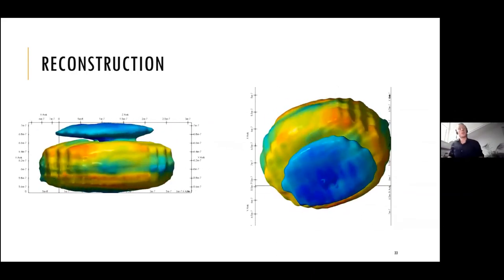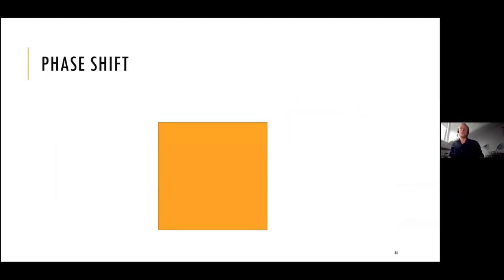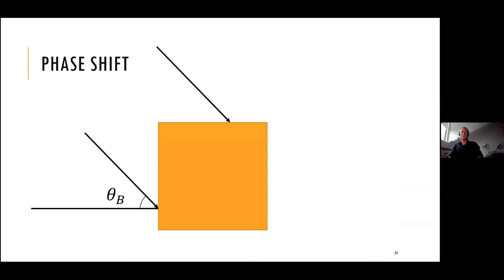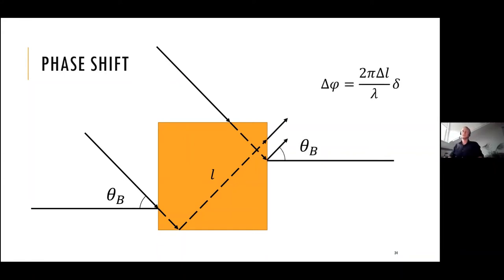Another important aspect to correct after the reconstruction is done is, if your object is three-dimensional, you will get an additional phase shift, which is nothing to do with the phase structure of your sample, actually. It's the difference in the path lengths of the scattered beams. Let's say the X-ray beams coming under the Bragg angle. But for different incidence positions, you will get different propagation distances of the X-rays inside your sample. And as a result, you will get an additional phase difference as an outcome.